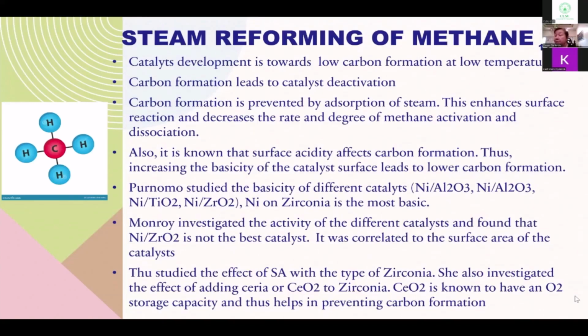So, our study focused on the effect of surface area of zirconia on steam reforming of methane. In addition, modification of zirconia support by the addition of ceria led to the improvement of oxygen storage capacity and thermal resistance, as well as the promotion of metal dispersion on the support. The catalyst we developed was compared to a commercial catalyst used in Indonesia. It was proven to be better in terms of lowering the process temperature and preventing deactivation due to carbon formation.